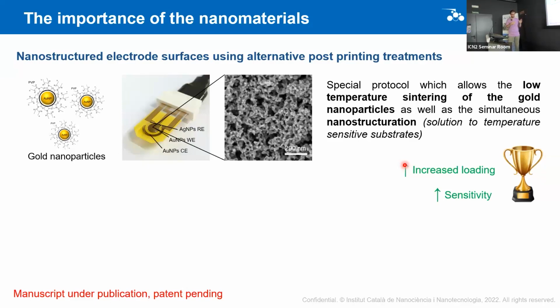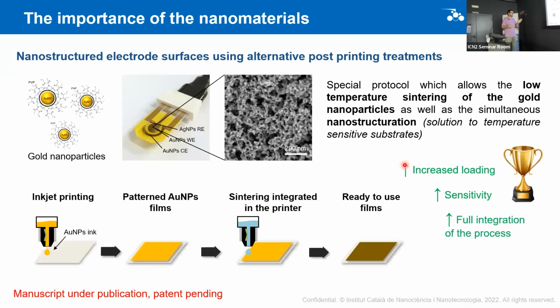So you have a really porous structured electrode, which for biosensing purposes is really good because it increases the loading of bioreceptors that you can have, and also generally the sensitivity and analytical performance values. What we also showed in this case is that it's possible to integrate this in the same printer, so that you can print and then sinter at the same time. This integration inside the printer is also towards the goal of having a standalone device that produces the sensors, and you can have it in your place.